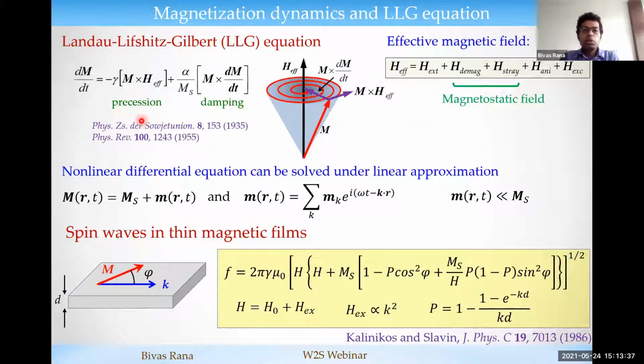Okay. So now how to solve this nonlinear differential equation? Well, one can do it by linearizing, under the linear approximation of the spin wave. So what is that? Basically, you can write the magnetization, which is varying in space and time, in terms of the saturation magnetization, which is constant over time, plus a dynamic component of magnetization. Here this small m is much smaller than Ms. Under this condition, you can write this m as a combination of several linear spin waves having different k vectors and frequencies. If you put this into this equation, then you can get the solution for the spin wave frequency.